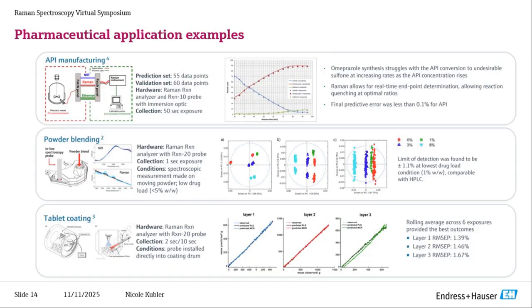Tying into the workflow in the previous slide, this slide here highlights the various applications with the design of experiments. The first one here is API manufacturing, where Raman demonstrated real-time endpoint determination, allowing reaction quenching at optimal ratios. The second here is powder blending, where measurements were made on moving powder to ensure homogeneous mixture where a non-contact measurement was established. And the third, tablet coating, where the probe was installed directly into the coating drum to measure coating composition and uniformity.